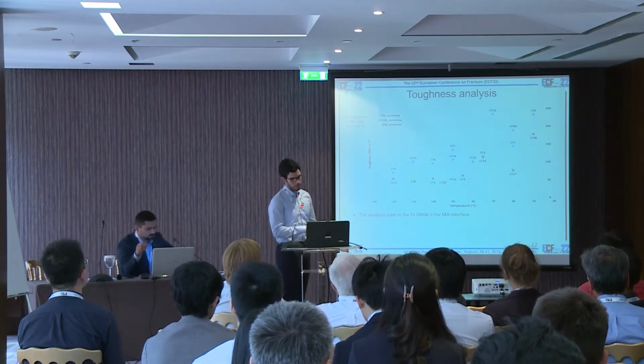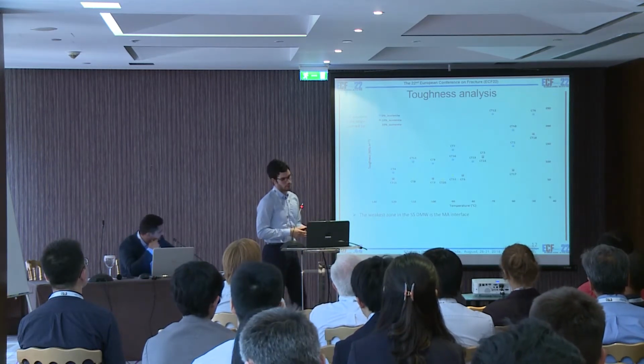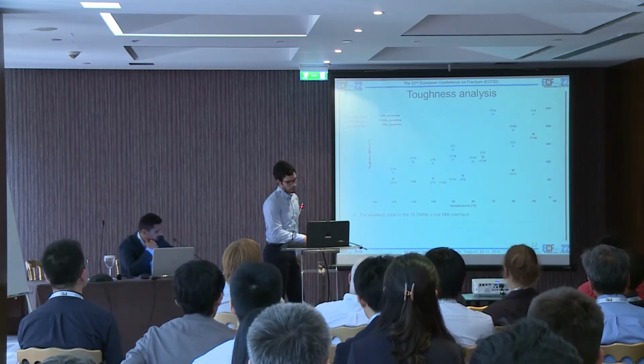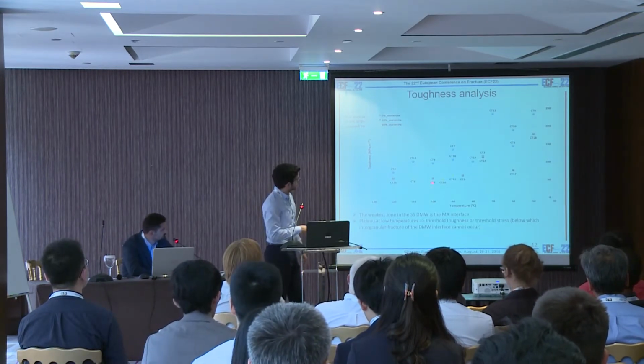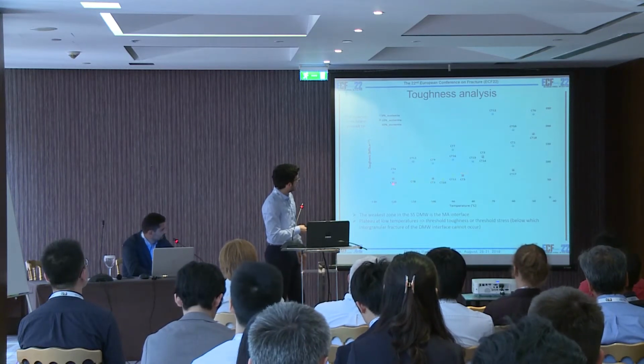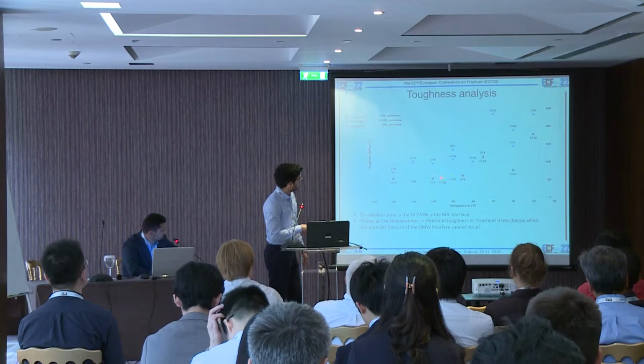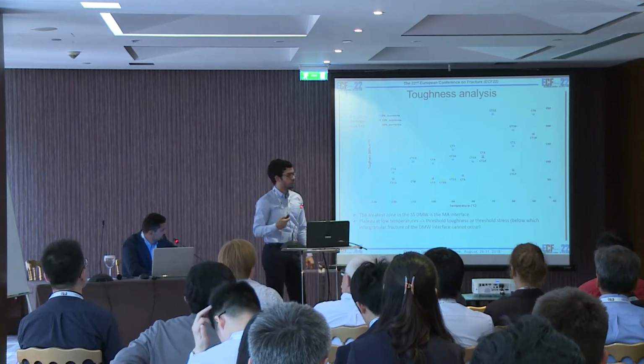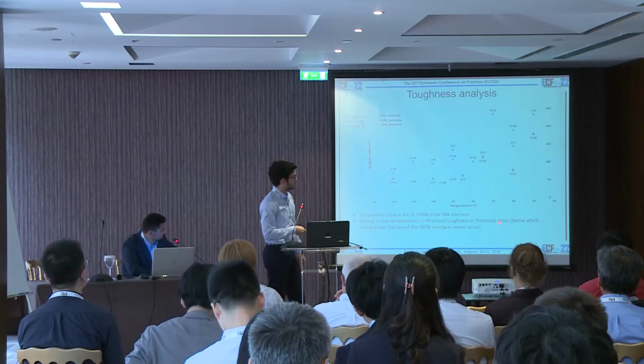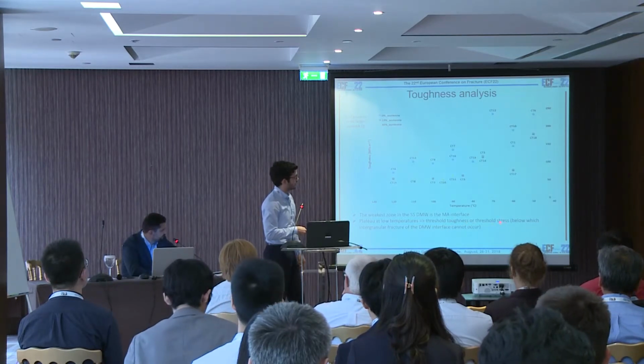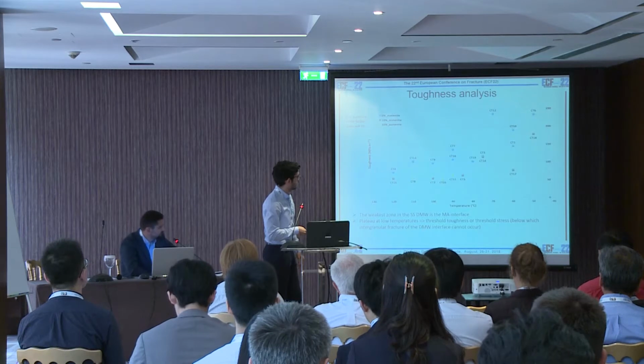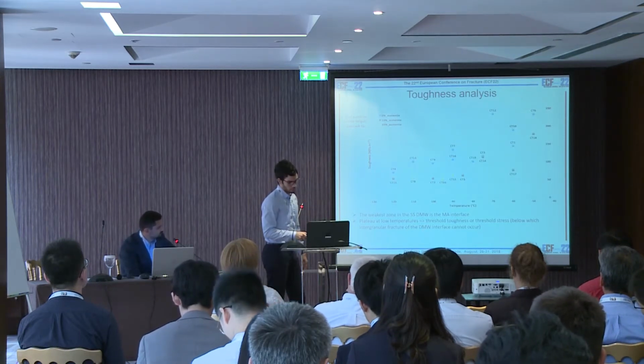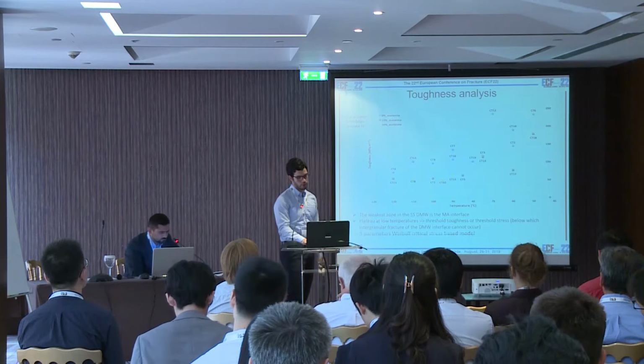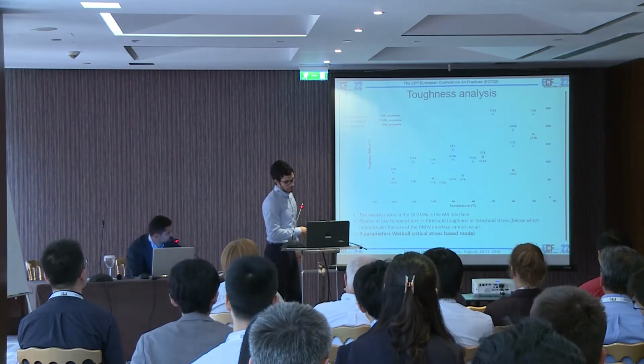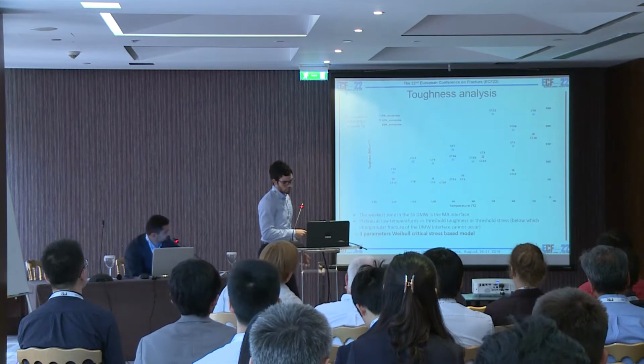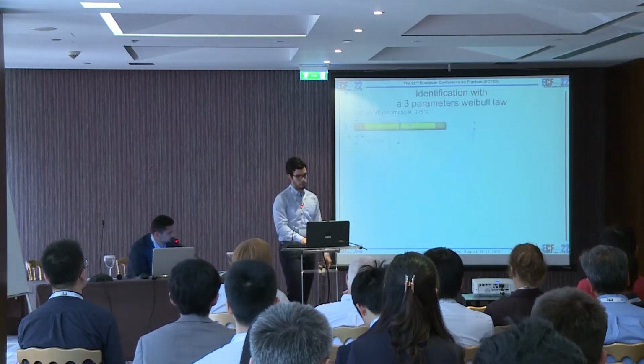So which emphasizes the fact that the weakest zone in the SSDMW is this MA interface. And furthermore, we can see, if we look just here, that we have some kind of plateau at low temperatures, which is consistent with the notion of threshold toughness or threshold stress. So which is the stress below which intergranular fracture of the DMW interface cannot occur, which is widely introduced in the literature. So a 3-parameter Weibull critical stress-based model seems a good choice to model this brittle fracture.